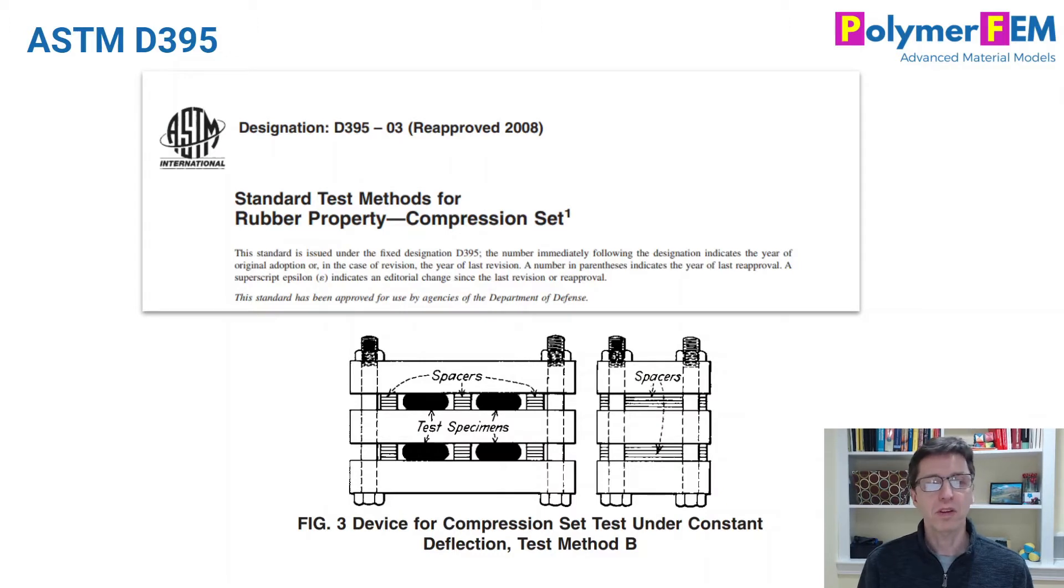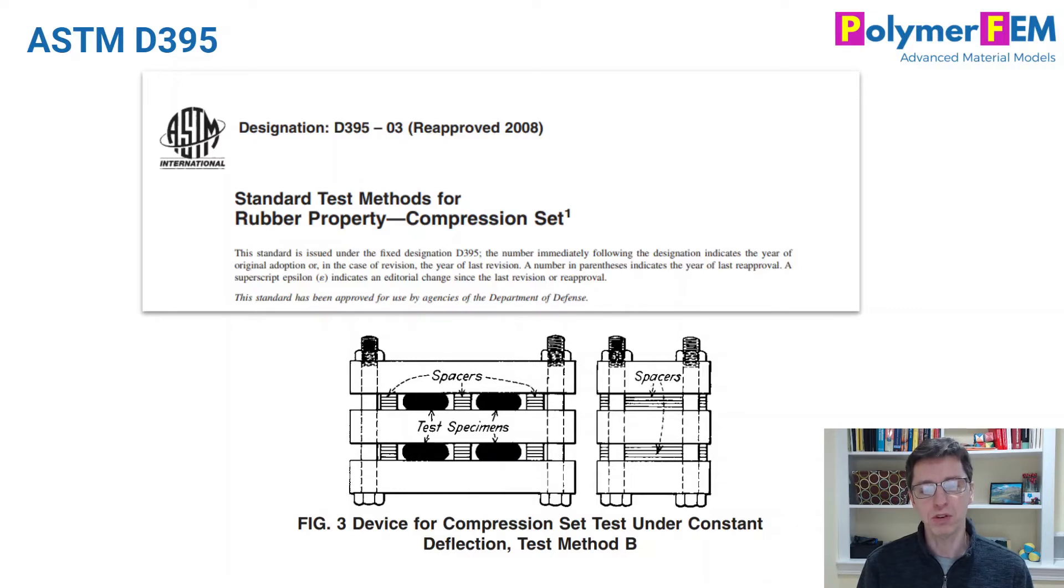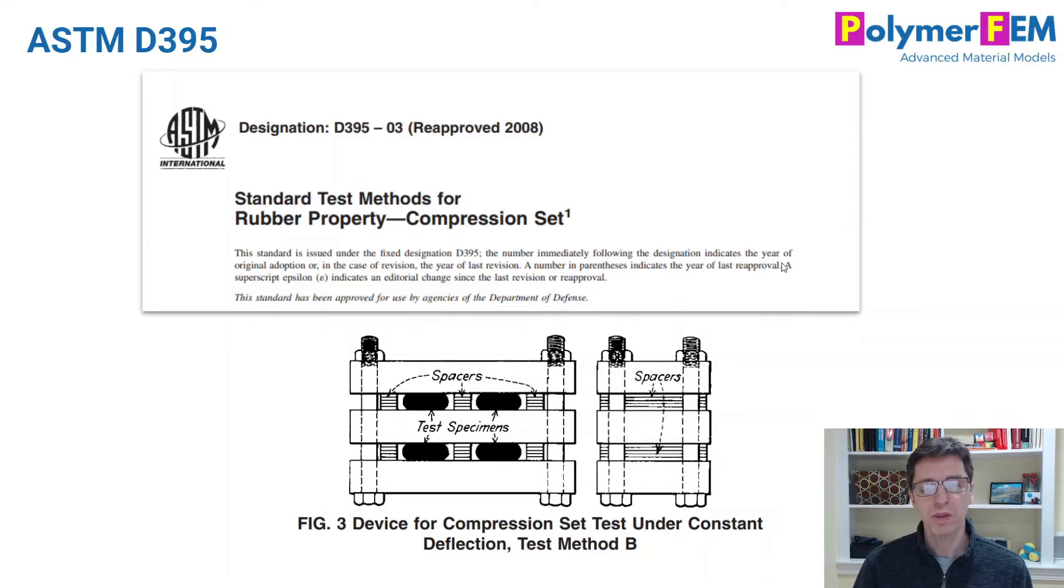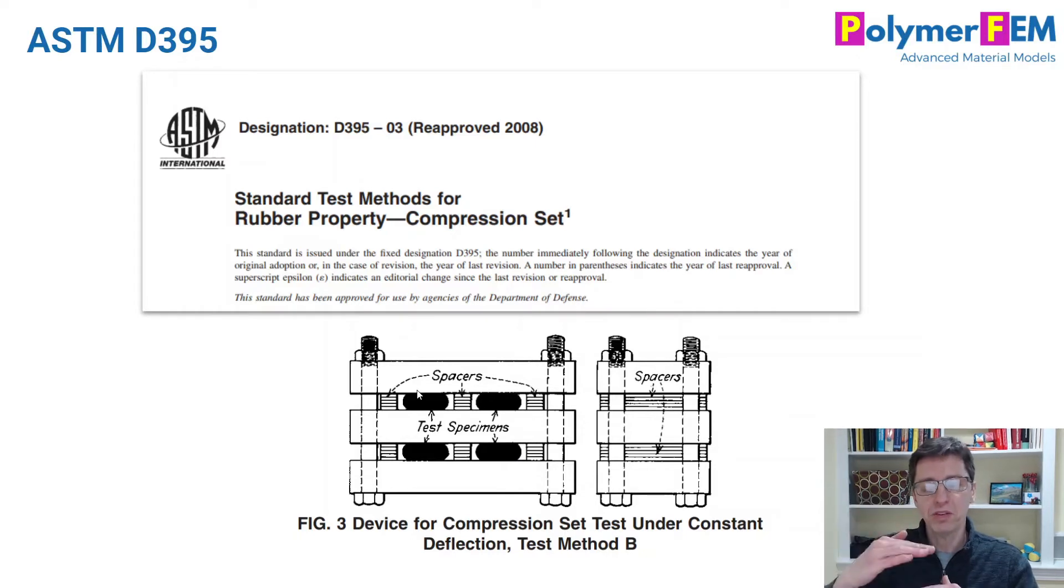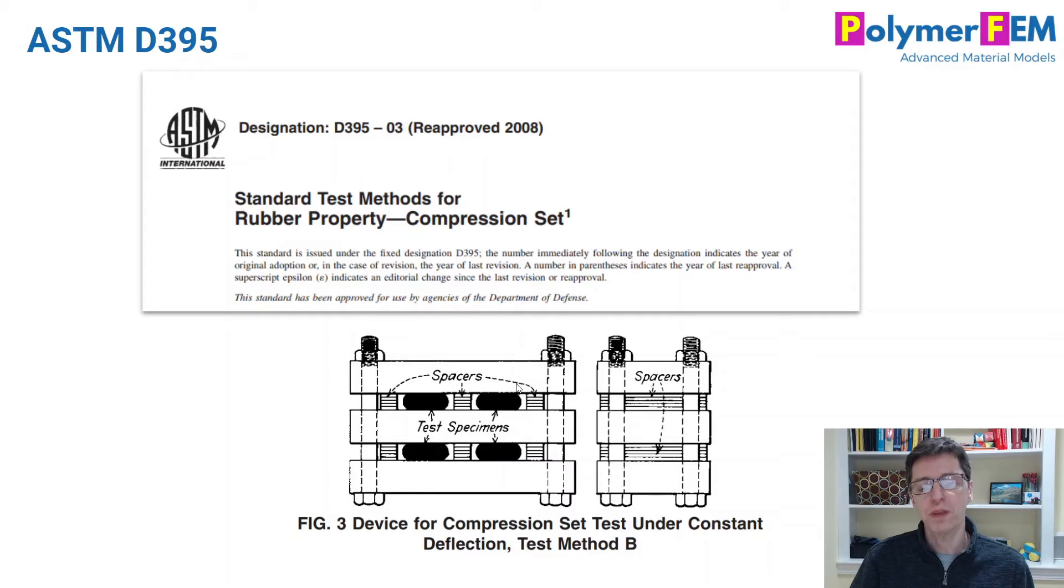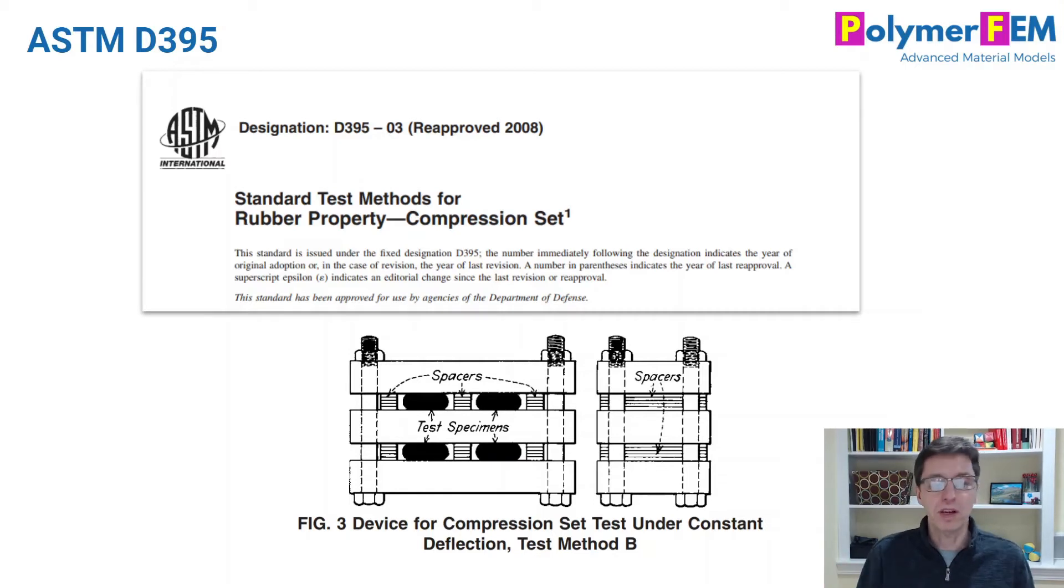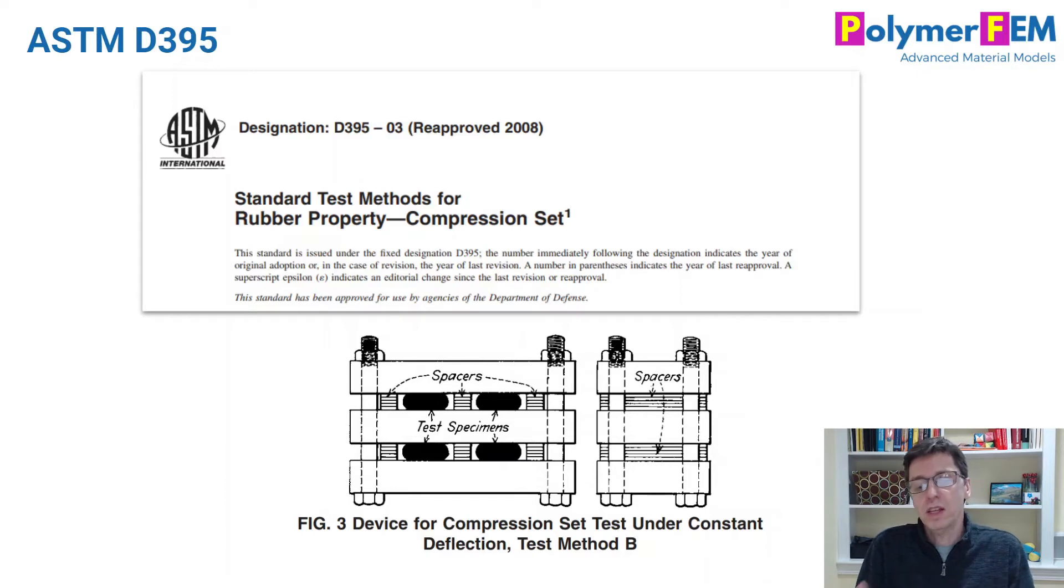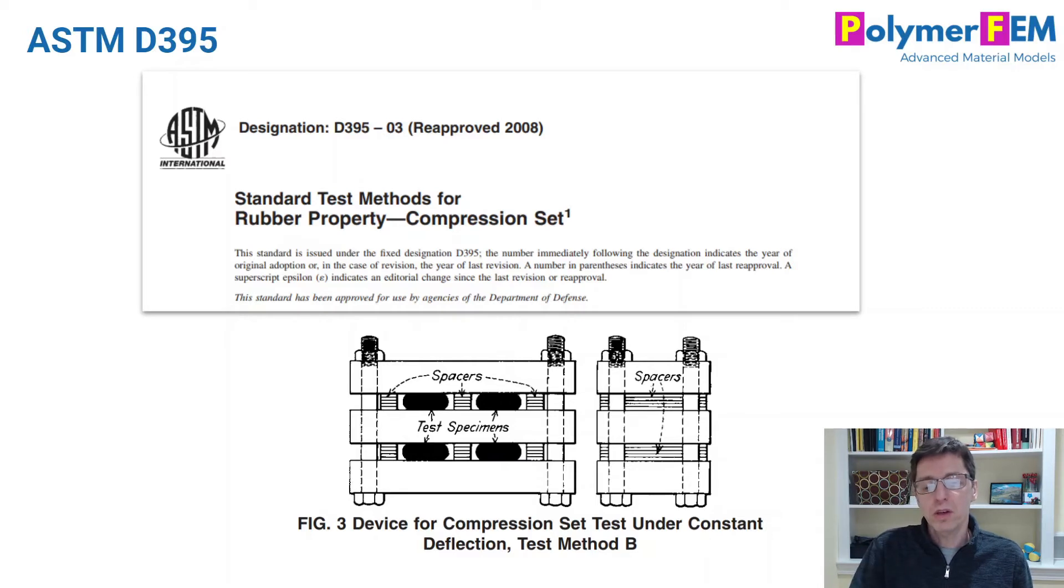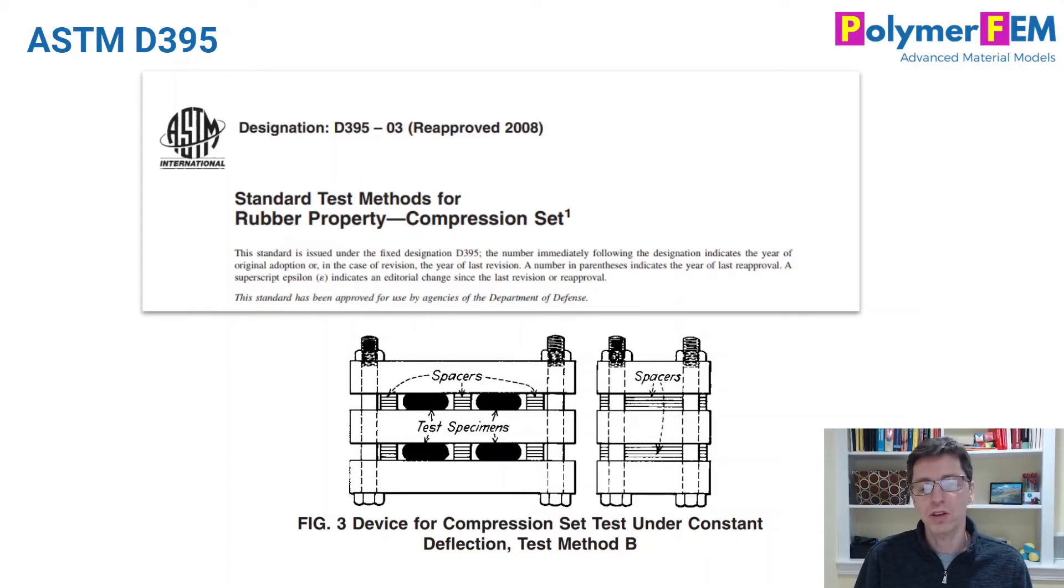What you need is, what I recommend at least, is the ASTM standard D395 for compression set testing of rubbers. And this is one of these experiments that is really nice because it's so simple to do and it gives you exactly the kind of information you need. And here's a screenshot from the standard itself. You have these spacers and you have rubber specimens that are being compressed between these spacers in this fixture. So you take your specimen, you tighten up the fixture, and the specimens sit in this fixture for long periods of time. And then you open it up. Sometimes they even sit at higher temperature for weeks or months. Then you take them out of the furnace or the oven. You open them up and you let them cool down.